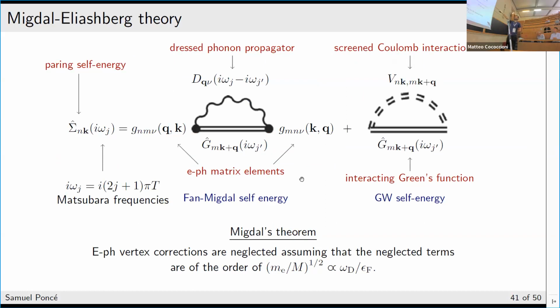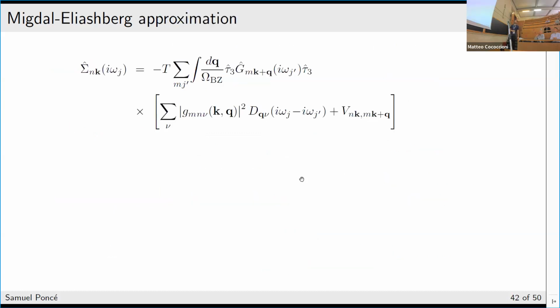Okay, and so we can then look at the electron-phonon self-energy, but this is a bit generalized because you have this Cooper pair, so it's actually called the pairing self-energy, and it has the usual Fan term, that is the same as for the normal electron-phonon. So this is the dressed phonon propagator, this is the electron, and then the g are the electron-phonon couplings. But you also have a screened Coulomb interaction. Basically we can express this pairing self-energy in terms of our Green's function. Now we have these Pauli matrices because, remember, it's a 2x2 matrix, and so we basically have the sum of those two Feynman diagrams. One is the Fan electron-phonon coupling, and then we have the electron-electron one.